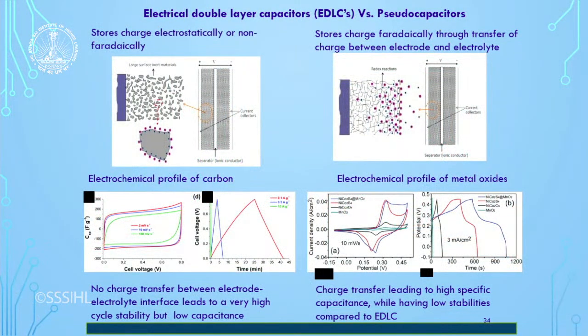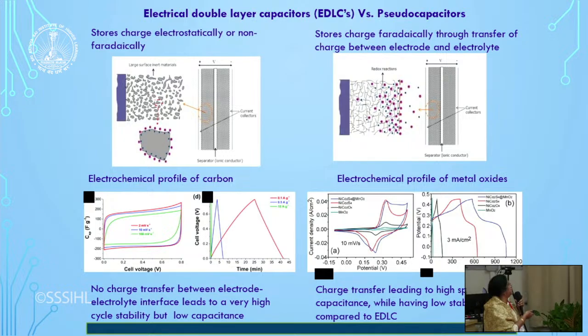But after the lithium ion battery, supercapacitors for the high power applications, you can see over here, there are 2 types of supercapacitors, one working completely on EDLC, that is electric double layer capacitors, just like capacitors. And the other one is on redox behavior, that is it oxidizes, you keep a small metal oxide particle along with carbon, and that gives a redox behavior, and you can see that the current density is very high, which results in very high specific capacitance. And one more advantage over the carbon supercapacitors is that it is useful even for biomedical devices, because it makes use of only aqueous electrolytes, unlike the carbon-based EDLC supercapacitors. So now we also worked on this.